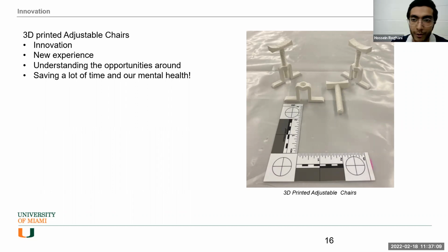But I'm not sure if you have ever tried to implement rebars in concrete. There are some plastic and steel chairs available in the market, but they have a specific depth, which was not appropriate for us. Every time we had to grind them, cut them, and put them beneath the rebars and make sure that they are working. And it was a real pain in the neck. Each time we wanted to cast our specimens for 3 slabs, we were spending like 3 days just to implement the rebars. 3 days was really hard.